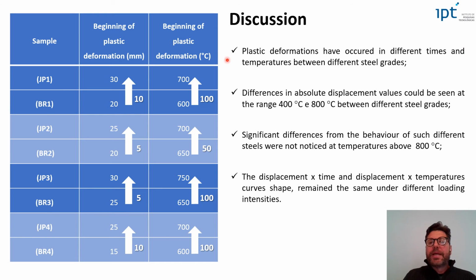For the discussions, plastic deformations have occurred at different times and temperatures between different steel grades. Differences in absolute displacement values could be seen in the range of 400 degrees to 800 degrees between different steel grades. Significant differences in the behavior of such different steels were not noticed at temperatures above 800 degrees. And the displacement versus time and displacement versus temperature curve shapes remained the same under different loading intensities.